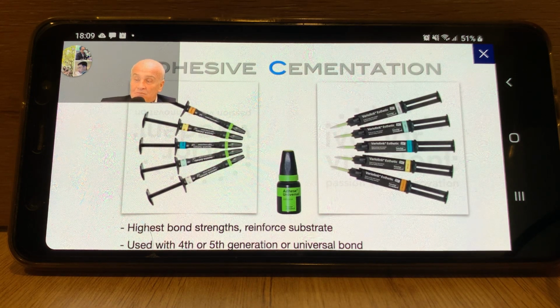And then we come to what is probably the oldest material that we have in terms of adhesive resins for cementation, and that is the resin cement with a bonding agent, with a dentin bonding agent. This material, as opposed to the others, although it comes in a dual cured form, also comes in a light cured form. And that's important because when you're cementing, especially veneers, you really don't want to use a dual cured cement. You want to use a light cured cement. You want to give yourself adequate time, and there's plenty of possibilities for curing this material. In the posterior, you can use light cured cements. You could actually use heated composite. Many people have used that. I use that occasionally, but there is always a question about whether your light curing unit will reach